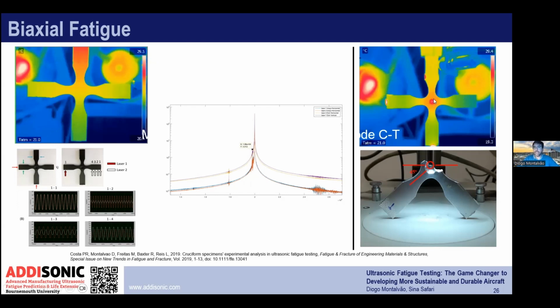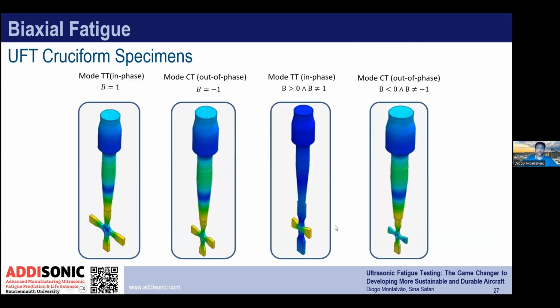And once that's done, we can see that we're getting good data. The maximum stress is at the center. And in this case, the fracture was around 45 degrees, which, as this is a pure shear specimen, is exactly what we expect to get from theory.